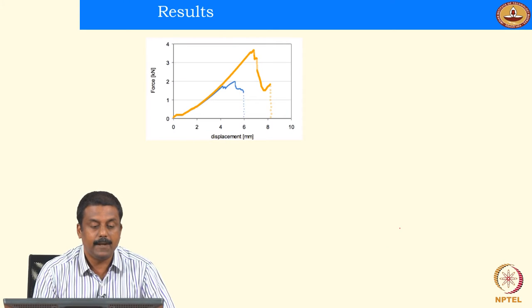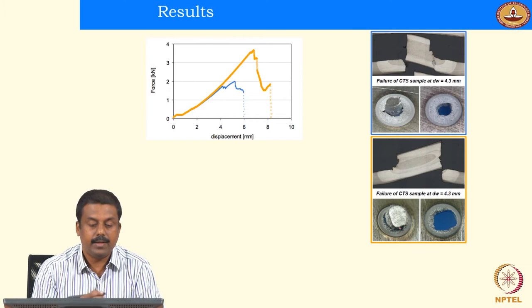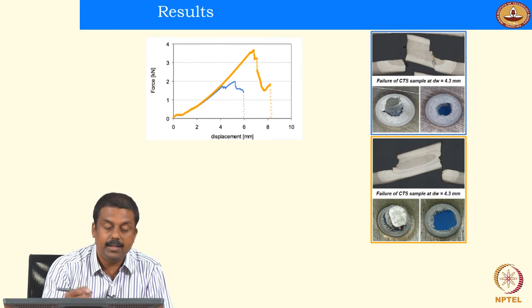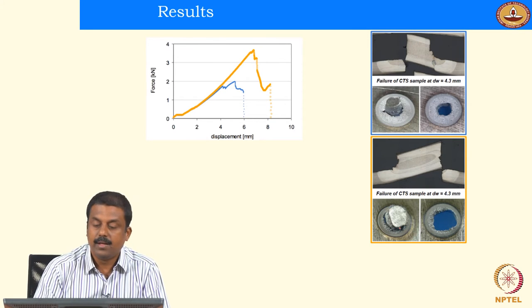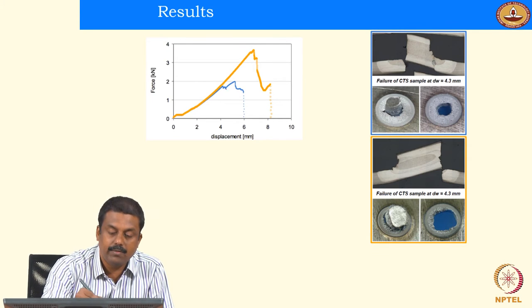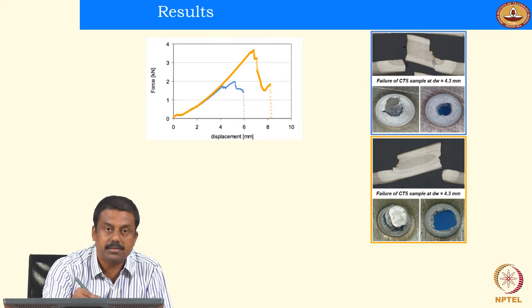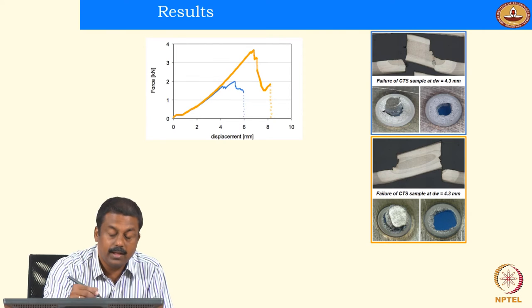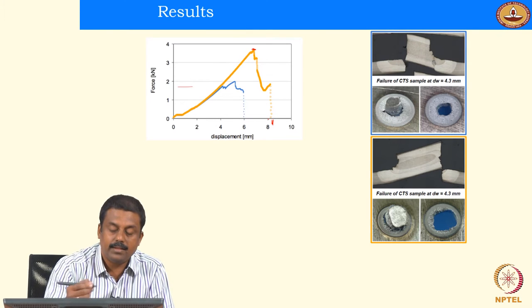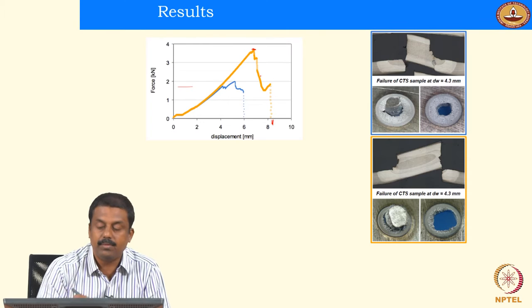You clearly see in the curves that the mechanical properties certainly improve. For example, the blue curve here shows the cross tension test results, where the first pulsing shows very poor strength, whereas after applying a second pulsing, your strength level increases significantly. You also have a high displacement. That means that the mechanical properties improve significantly.